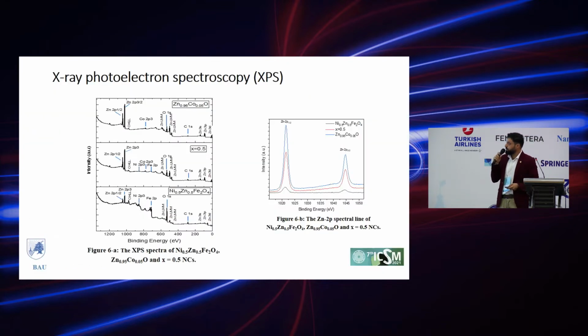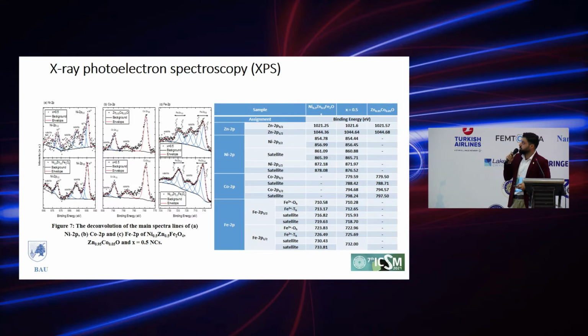In order to detect the elemental composition of all samples, X-ray photoelectron spectroscopy was performed. All samples have shown the presence of all elements, and a deconvolution of the spectral lines of zinc, cobalt, iron, and nickel was done in order to determine the oxidation states of the elements. Zinc was found in an oxidation state of +2. Nickel was found in a mixed valency of +2 and +3, cobalt with a valency of +2, and a valency of +3 was assigned to Fe in both octahedral and tetrahedral sites.